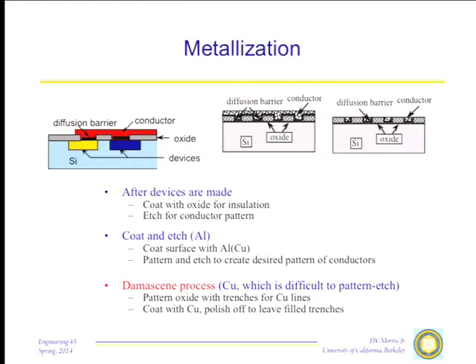Another disadvantage to aluminum was that it was liable to electromigration. Now, I don't have time to go through that in great detail, but essentially what's happening is you start pushing current through these devices. Even though the current is very small, when the devices become very small in cross-section, the current densities become very high. When current is going through a device like aluminum, it has a tendency to push the atoms along with it. So you have atoms moving with the current, vacancies going in the other direction, and you can develop vacancy agglomerations which lead to actual failure of the devices.